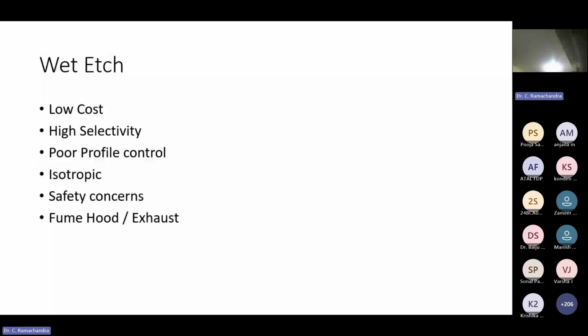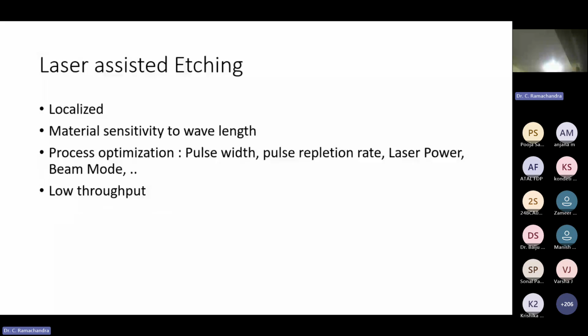Then laser assisted etching. This is also ambient because most of the laser passes through the atmosphere, no problem. But it is localized. That means you want to etch a specific part of the material of a few micron size. It is not for the whole wafer. It is localized and material sensitive to wavelength. Different materials absorb lasers of one particular wavelength. Therefore, it is possible to etch maybe silicon oxide, but not silicon nitride. This kind of selectivity is possible by choosing the proper wavelength.